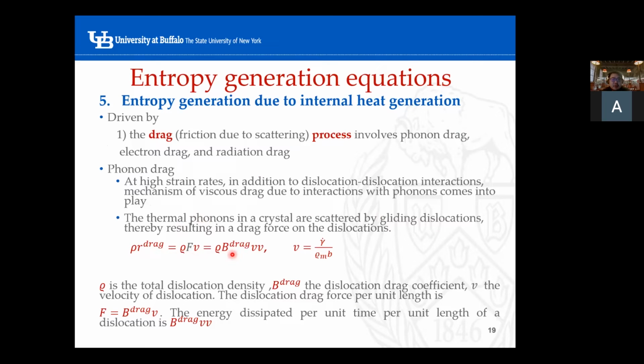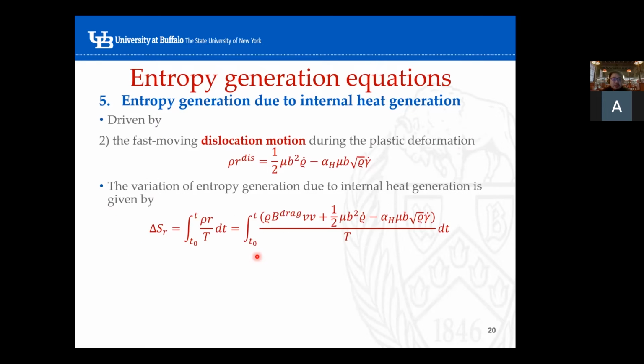Heat generation due to drag, phonon drag, and the heat generation due to dislocation motion - by combining these 2, we find the amount of entropy generation due to internal heat generation will be this combination of these 3 terms, and they are strain rate dependent because V is related to shear strain rate, and this one is also related to shear strain rate. So the shear strain rate affects this term. In ultrasonic vibration fatigue, we have high strain rate and high frequency, so this equation has to be considered.